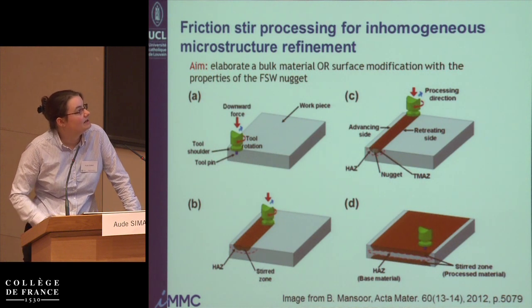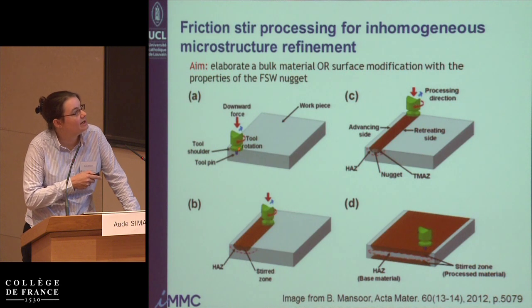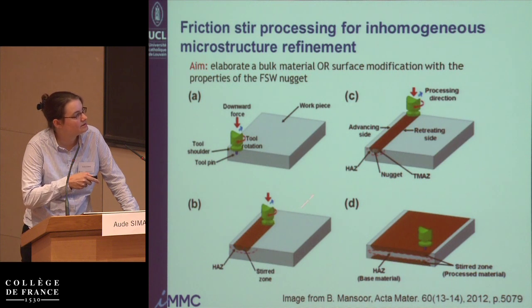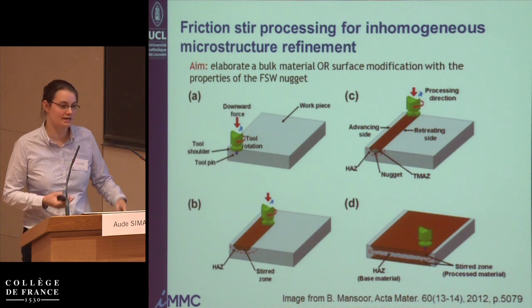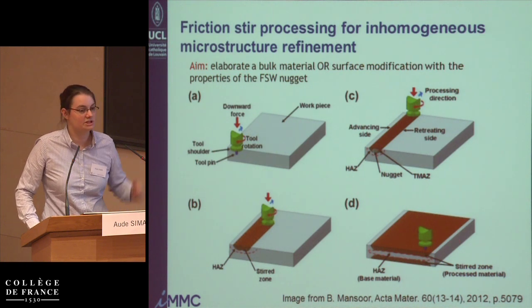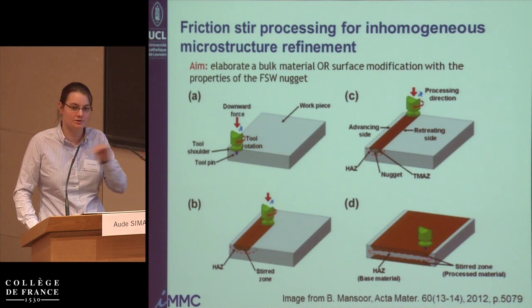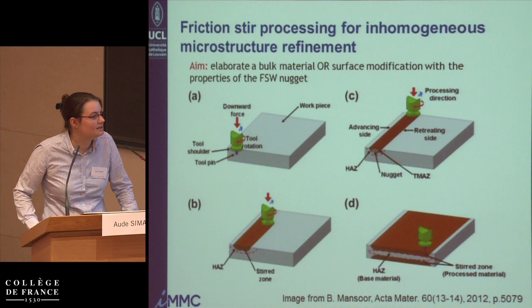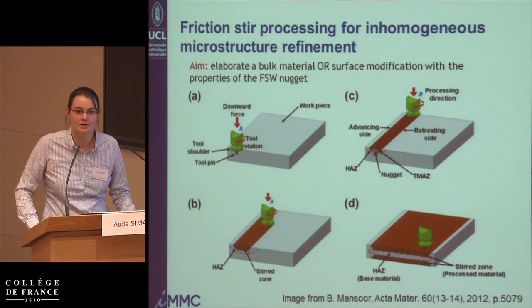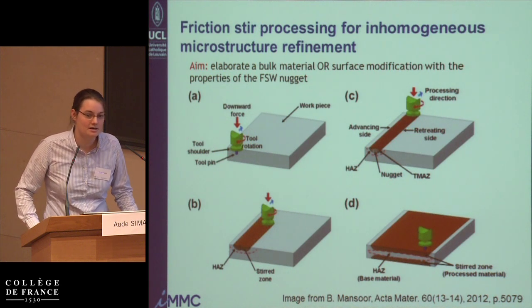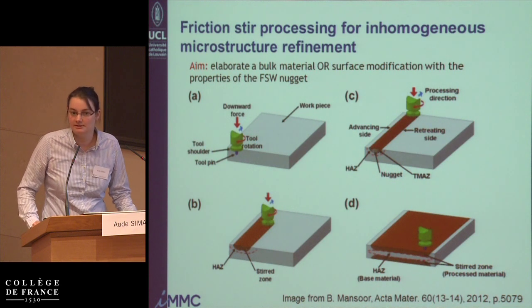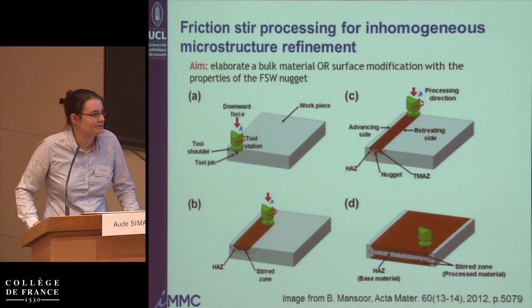And so what you do is you have your tool, and you enter your material, and you go for a first round, then you go back next to it, second round, and so on, and then turn over your plate, and you can have a sandwich with nugget material on top, some base material in the middle, and nugget material on the bottom. So you're making a sandwich material without actually joining anything, but just by processing the material.